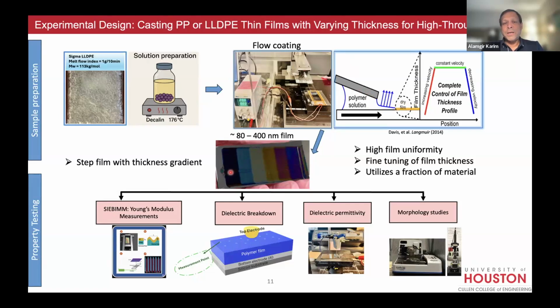And this is very cool because you can measure on a single substrate. The bottom could be an aluminum electrode on a silicon wafer. And so you can measure simultaneously, on one single chip, all the breakdowns for different thicknesses, okay? I used to run the NIST Combinatorial Methods Center. These are the kind of techniques we developed. We have a large number of papers on this sort of flow coating method to make polymer films, to study adhesion, crystallinity, height, you name it, phase behavior, block copolymer assembly, and so on.